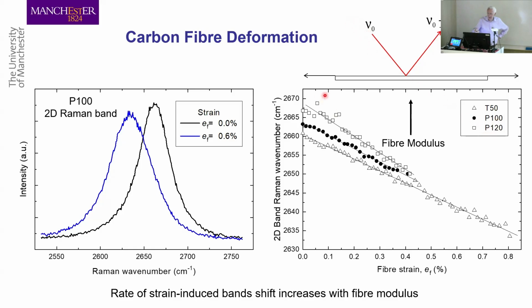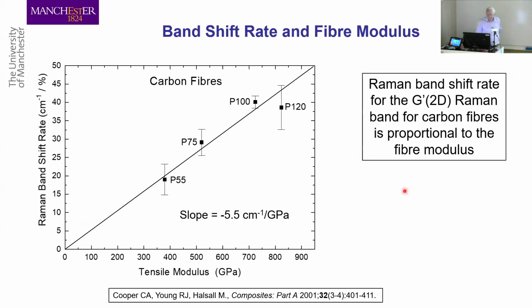Here's our technique. We just take a single fiber, we stretch it, we shine the laser on it and just look at this peak shift. Very simple experiment. It takes about 10 seconds to obtain this peak. It's a very quick technique, just to obtain the spectrum in a modern spectrometer. And what we found was that if we plot the slope of these lines, which is peak position against strain, against the tensile modulus of the fiber, so this is now the shift rate, the slope of the line, against the fiber modulus, you get a sort of roughly linear relationship.